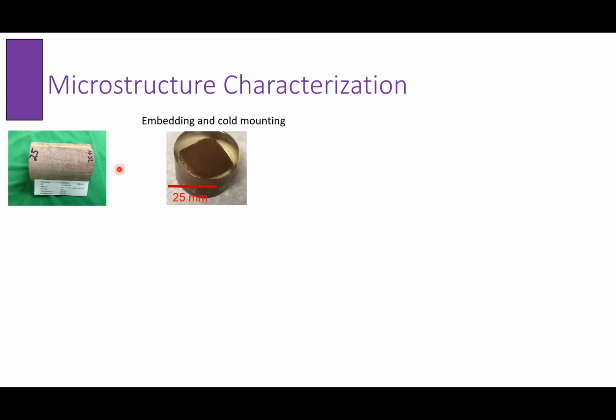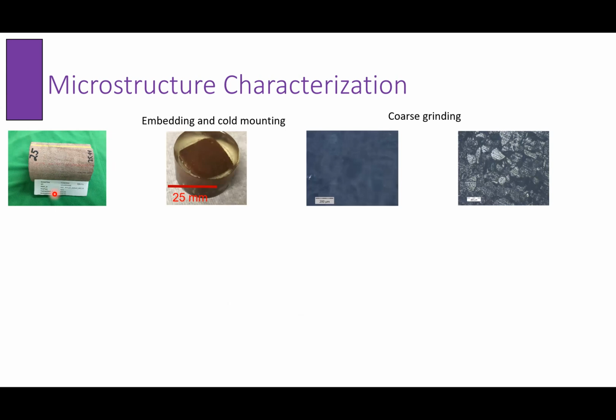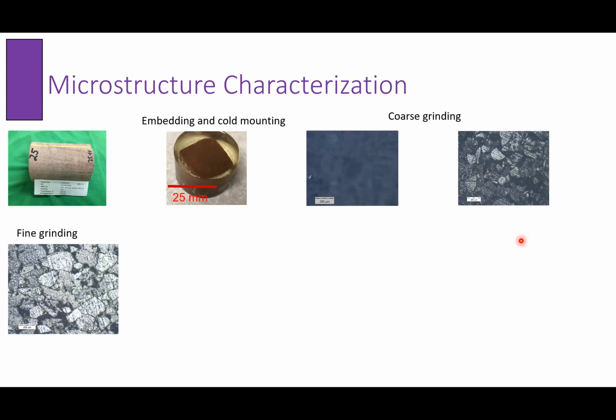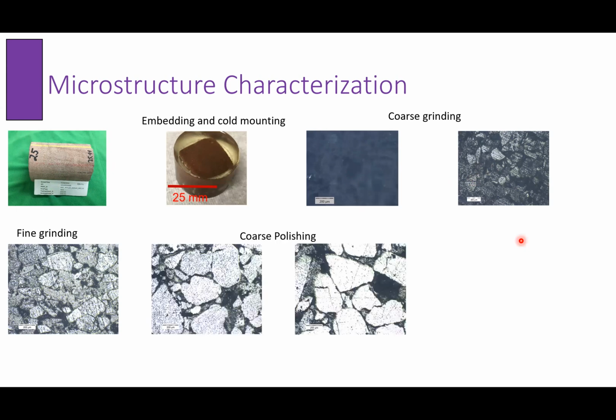We have the host rock, that is Mount Simon sandstone, that was extracted from 2,500 meters underground. Then we embed it with low viscosity epoxy resin. Then you're going to have coarse grinding. We have different stages of coarse grinding, different stages of fine grinding. Then we have coarse polishing, and we have fine polishing.